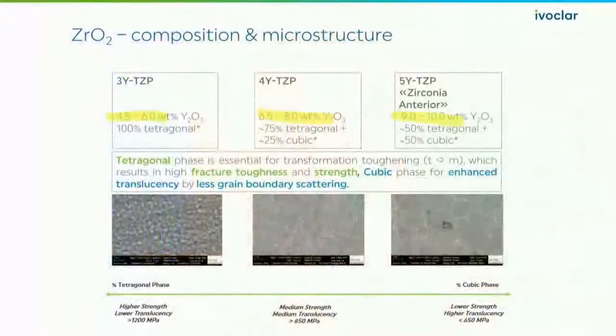So the 3 big ones that are out there: the 3Y, again, 100% tetragonal phase; the 4Ys, a little more translucency, about a 75% tetragonal phase; and the 5Ys, the higher translucency, about a 50-50 mix. So obviously with that comes degradation in strength. You get more translucency, but you lose strength. And you also lose that fracture resistance, kind of like I talked about with Ivotion, that fracture toughness. So as you move down, it becomes easier to break.